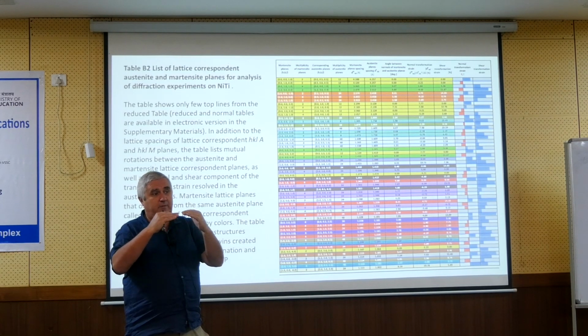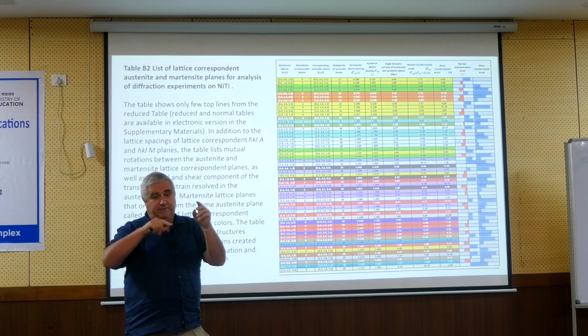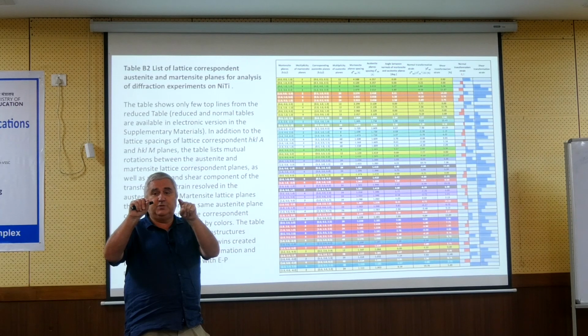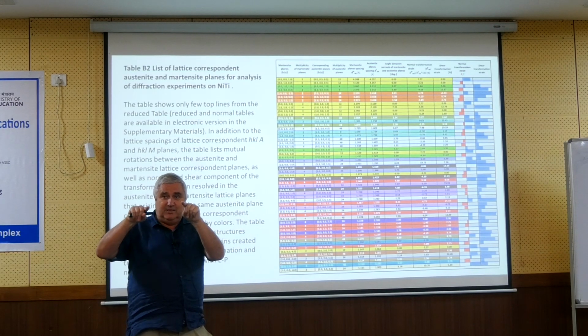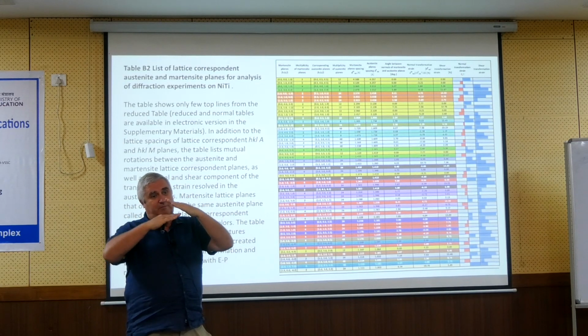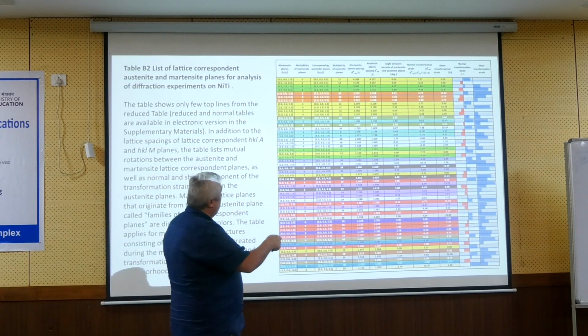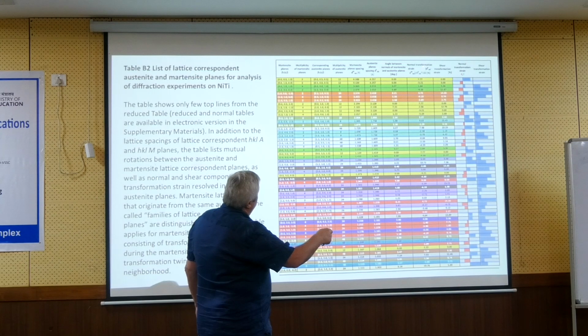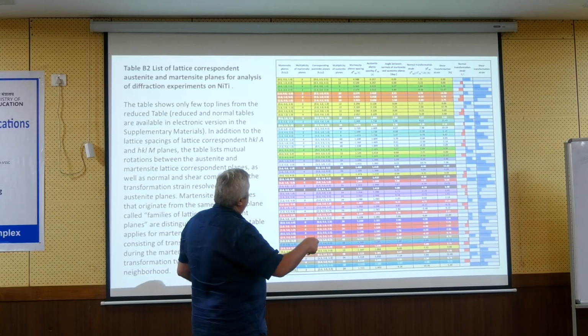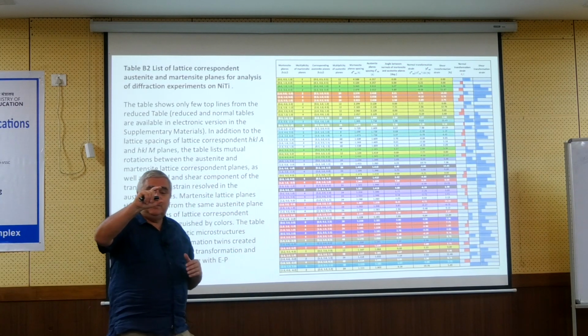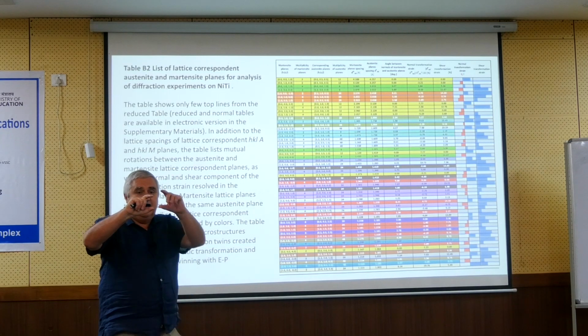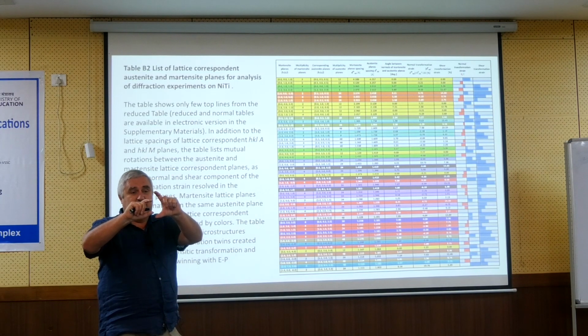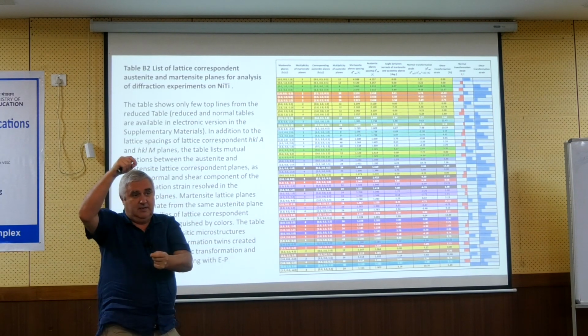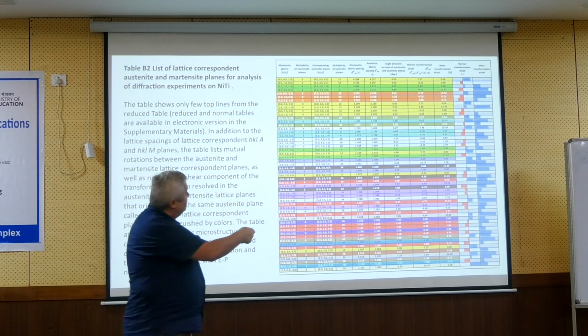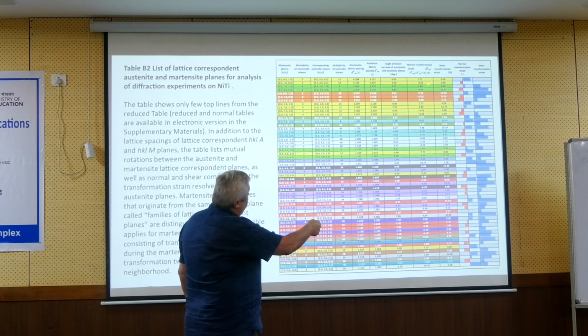Yeah? So in TEM images, you have a diffraction pattern. You have a spot from the austenite, and the spot from the martensite is slightly beside it, and this rotation means you have misorientation of planes. If I have this lattice spacing in austenite and this lattice spacing in martensite, what does it mean? It means extension. So this extension strain or compression strain is here.